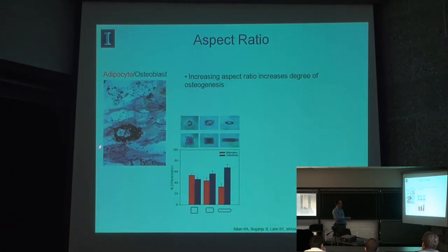One would promote fat, one would promote bone. And when you do that on plastic, you get this crazy heterogeneous mixture of cells. You have little pockets where you've got a lot of fat, a lot of bone in some regions. It's quite variable. When you pattern the cells, you can just go across the surface and count cells that either express bone markers or fat markers or both. And there tend to be a small amount that presents both, usually less than 5%.